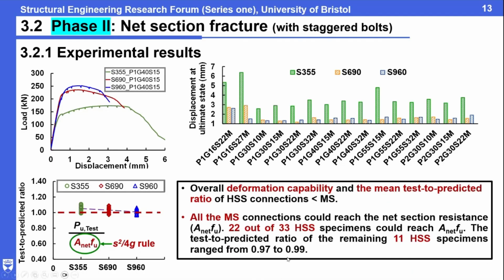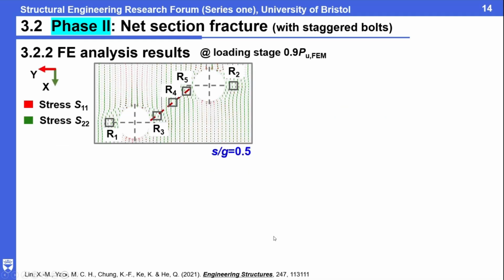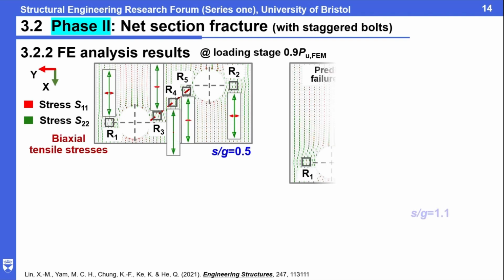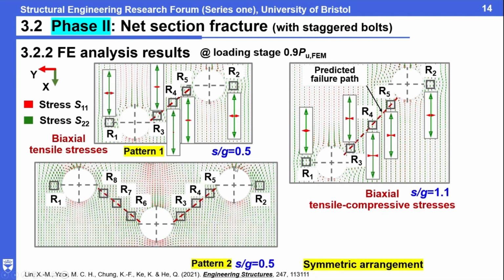For the staggered specimens, we have a total of 33 high strength steel specimens, and 22 nearly reach it, but 11 are a little bit lower, though nearly to 1 already. But I still want to look further at why that happens. So we also plot the stress state at different patterns. The first one is S over G equals half. So what is S? What is G? S is the distance of the two bolt holes along the loading direction. G is the gauge spacing perpendicular to the loading. So this way is S, and this way is G. This is S over G.